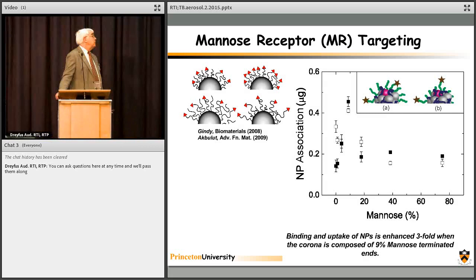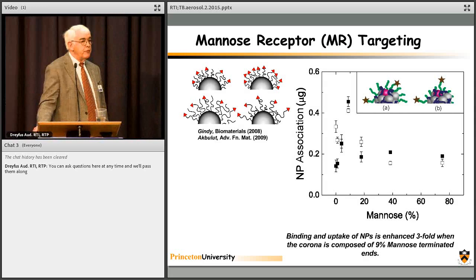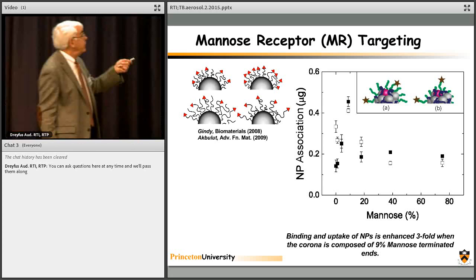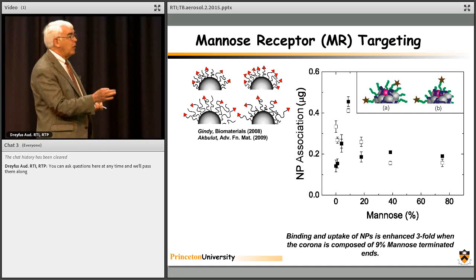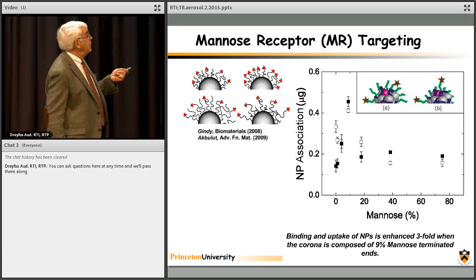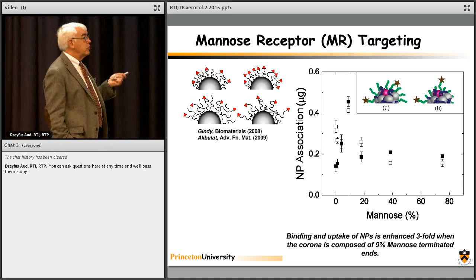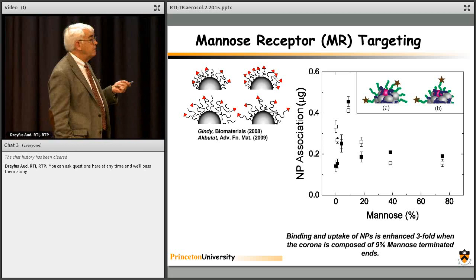Yeah. Rule of thumb, we can deliver 30 to 40 weight percent of the total nanoparticle weight can be drug for those conjugates I showed you. This is micrograms associated per 96 well plate bottle. In the paper, we do it per macrophage. But this is a 96 well plate, and these are the micrograms of nanoparticle which were internalized by all the macrophages in that. Okay, yeah, I think that sort of gets it. You have to translate that into how many millions of macrophages, but it seems like it's a reasonable approach.